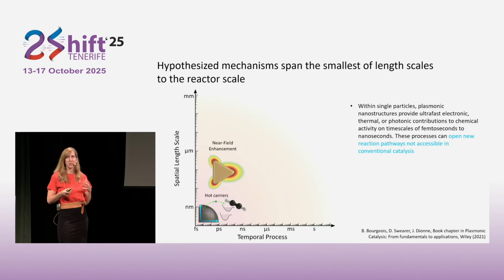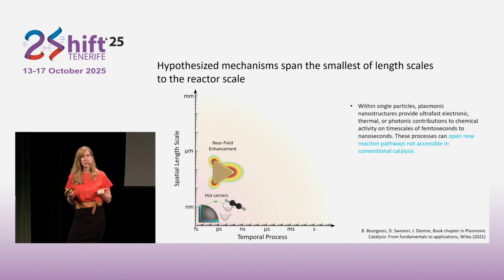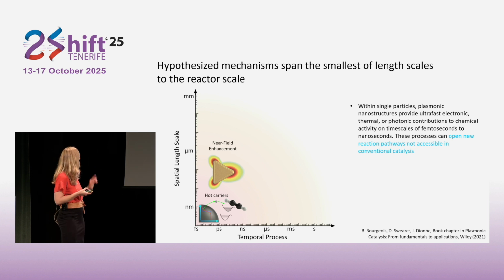And in terms of what more is going on, the hypothesized mechanisms span the fastest of time scales and the smallest of length scales all the way up to the reactor scale. So of course I mentioned you have these hot carriers. These are basically non-thermal distributions of electrons and holes that are being excited to energy levels that are distinct from the Fermi-Dirac energy distribution in the nanoparticle. And then those hot carriers can be directly injected into HOMO and LUMO levels of whatever your molecular adsorbates are during the reaction to drive particular reactions.